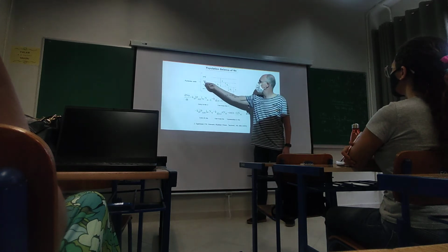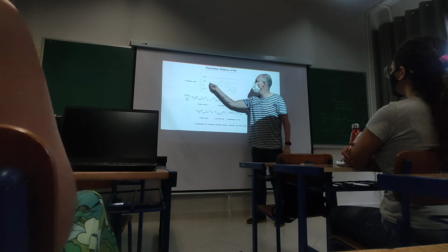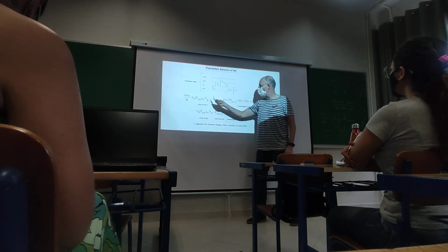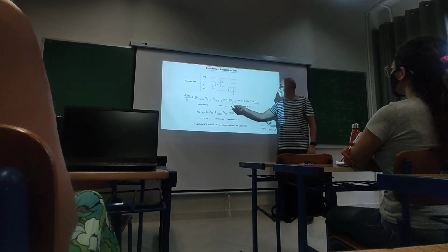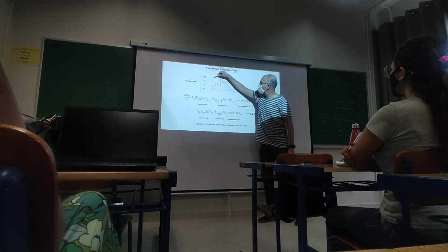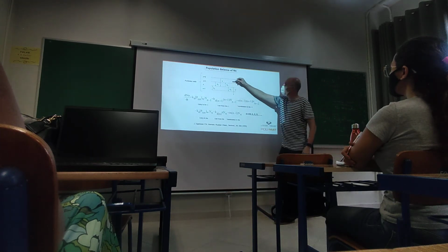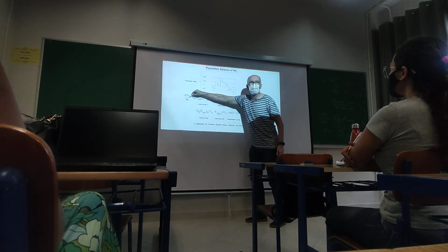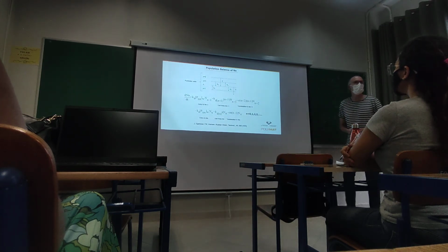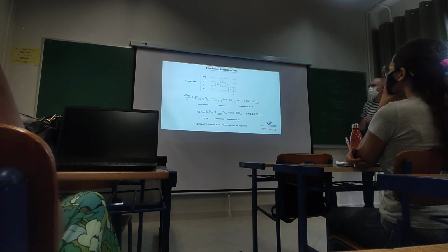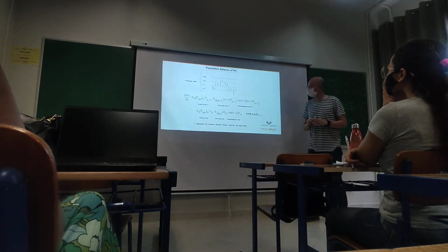If we have particles with n plus 1 and there is an exit of 1 radical, we will also form particles with n. So that's why we have this desorption or exit rate. And if we have particles with n plus 2, if there is termination, 2 radicals disappear, so that you will also form particles with n. So these are the 3 terms that give you the balance or the rate of formation of particles with n radicals.